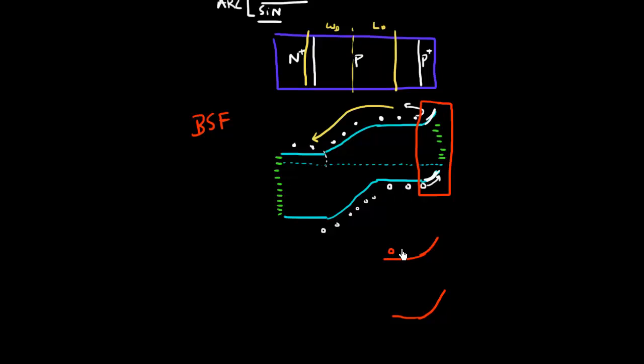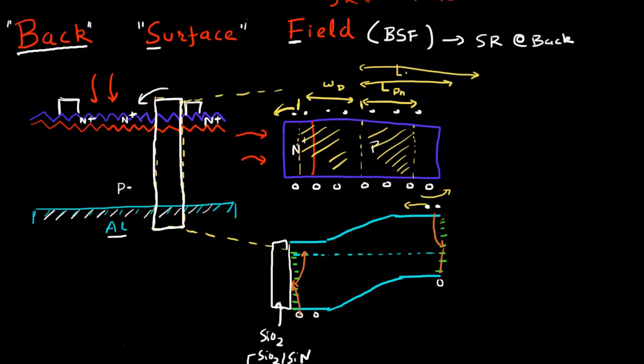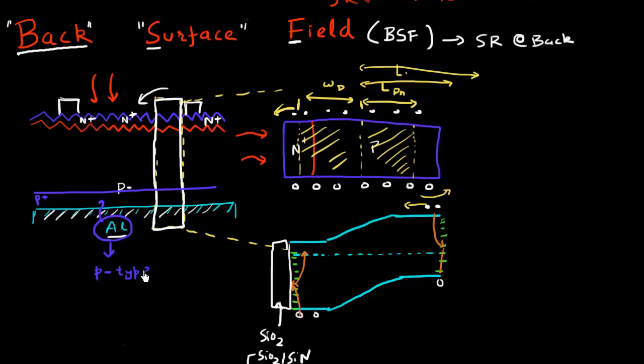The presence of this field is repelling these electrons from reaching the back surface. There are several ways to realize this back surface field. The most common and easiest way is P+ doping to create this back surface field. The easiest way to do that is to allow aluminum from the back — aluminum acts as a decent P-type dopant in silicon and creates this P+ layer towards the back, which repels the electrons from reaching the back surface. The other way would be to introduce boron, to do an implant or diffusion of boron from the back surface, to create this back surface field as well.